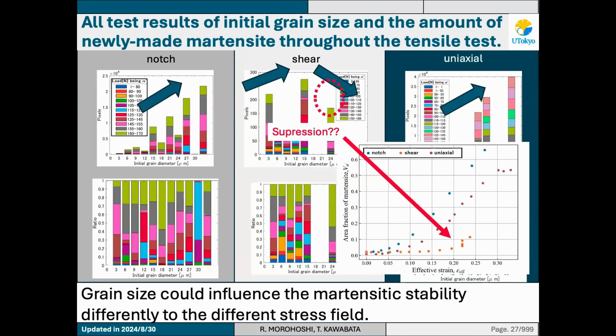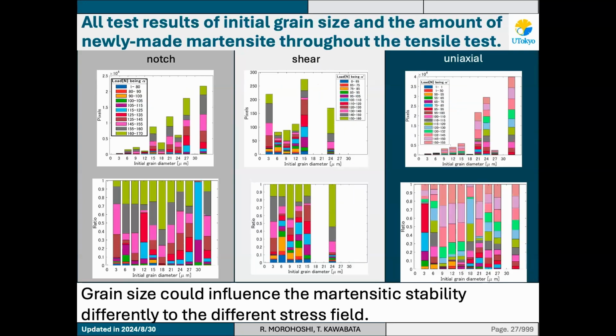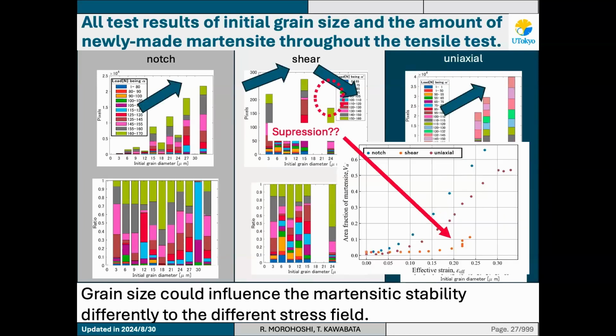In two cases, the x-axis shows the initial grain diameter and the y-axis is the amount of newly made martensite. In two cases, as the initial grain diameter increases, the newly made martensite increases. However, only in the shear case it didn't go like that. So maybe some kind of suppression happened that leads to the overall martensitic transformation. We think so, but it's just an assumption. So we need to do many more experiments to ensure that.